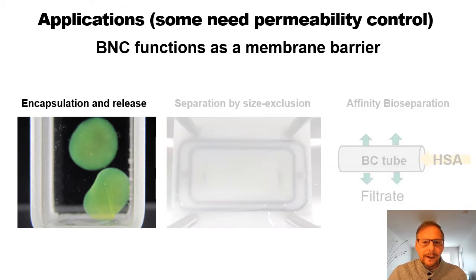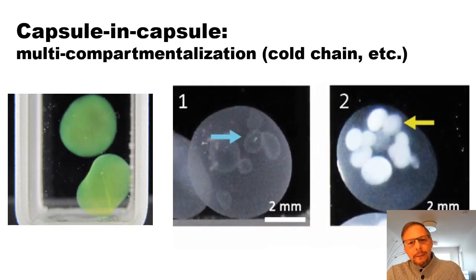So let me start with encapsulation very briefly. We're not going to go into detail, but in the case of encapsulation, you can imagine that these capsules that I have already introduced can be formed and immersed in water. If we take those capsules that contain water and are immersed in water, then we can prepare structures that are a little bit more complex. In this particular case, it's quite easy to produce capsules inside capsules. In both cases, they are produced by microorganisms. They are all cellulose, but in this case we're protecting smaller capsules with larger capsules, and that we can call multi-compartmentalization.